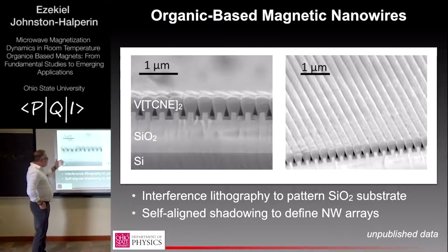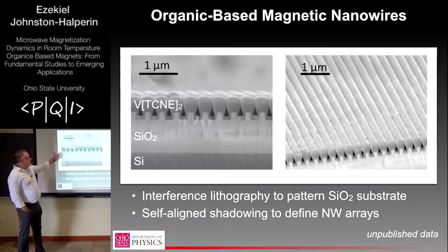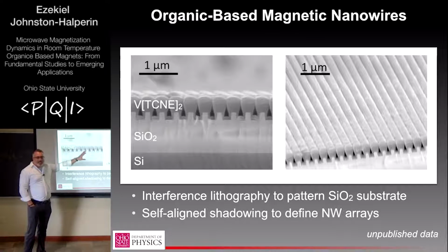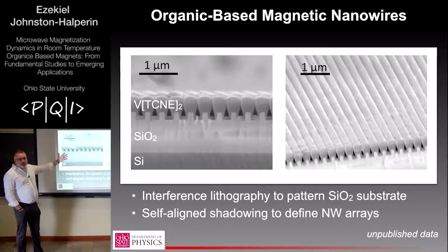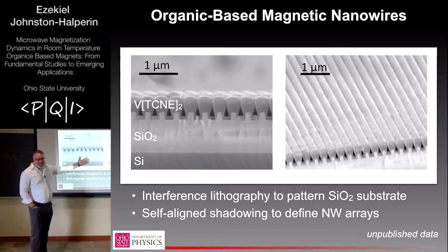just because the films as deposited have no in-plane anisotropy at all, and that's a degree of freedom we'd like to have. So the first time we did a deposition, we just threw it in the SEM, so some of this is oxidized, but we just wanted to see what we've done, and we were very surprised to see this.